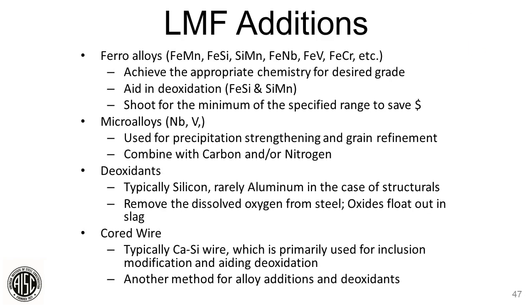All right, so then we're going to add our ferroalloys. We don't add pure manganese, they're always alloys. So ferromanganese, ferrosilicon, silicon manganese, ferroniobium, ferrovanadium, ferrochrome all come as a ferroalloy. And we add that to achieve the chemistry for the desired grade. We add ferrosilicon and silicon manganese to kill the heat, get the oxygen out. And we aim at the minimum alloying element levels to get the strength we want, because if we add more, we're wasting money. We use microalloys, niobium and vanadium, which precipitate, we talked about that before, for strengthening and grain refinement. And they combine with carbon and nitrogen, so this is where we add those.